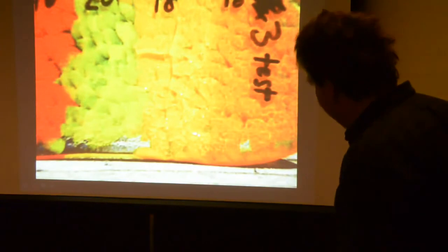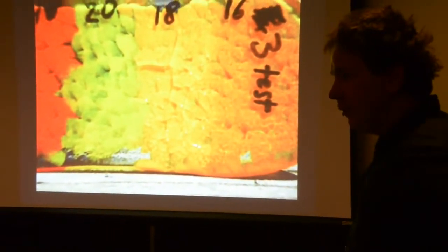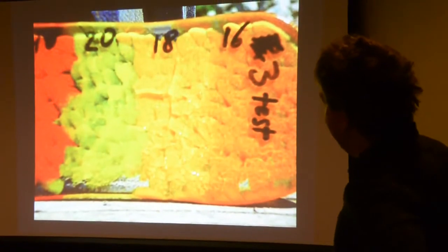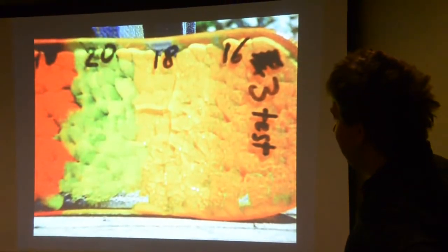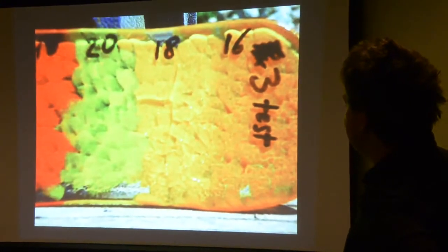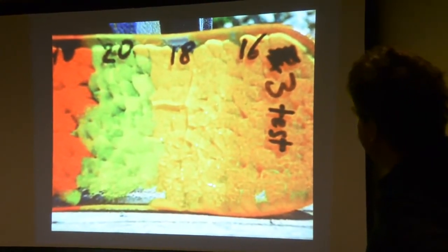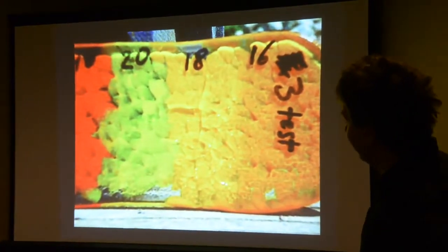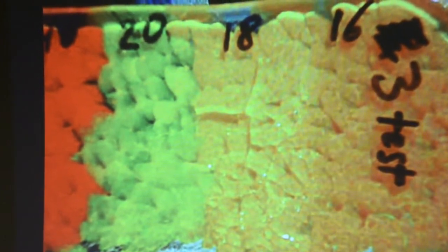This is a sample of how the glass colors can be incompatible with the base clear glass. In this case, this is double checking Reichenbach yellows against System 96 glass, where definitely number 18 is not compatible, even though it is sold as such. Those colors are pretty finicky, and the way those yellows are prepared, you're getting a colloid that comes out of the clear glass and forms these microscopic particles of yellow and orange in this case, and if you hold it at high temperature too long, these particles get larger and larger, you get a little more opaque, and it'll strike out, it'll turn dark brown.